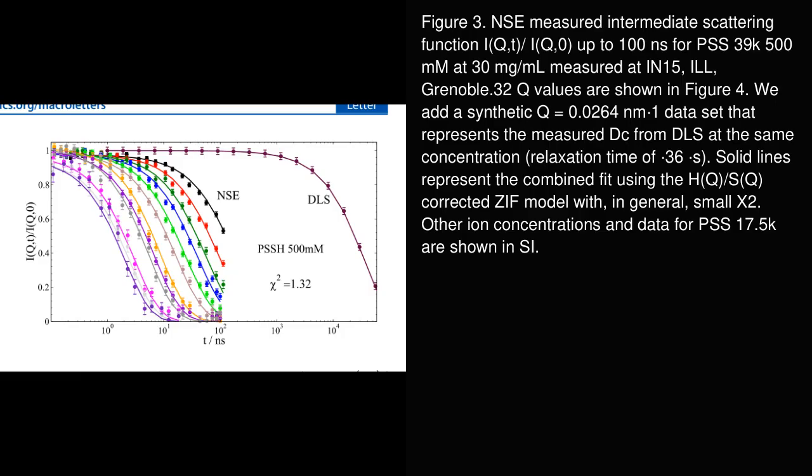The interpretation includes that increasing ion concentration tends to enhance internal friction, evidenced through NSE sensitivity at nanosecond timescales, whereas conformational changes occur due to electrostatic screening, indicated by changes in the polymer swelling exponent. Differences between polymer types and salt values influence hydrodynamic screening radius and interchain coupling, consistent with complementary DLS data. Overall, this figure provides a refined view of polyelectrolyte chain dynamics bridging collective and segmental regimes, characterized via advanced neutron scattering and modeled via the ZIF model with internal friction corrections.